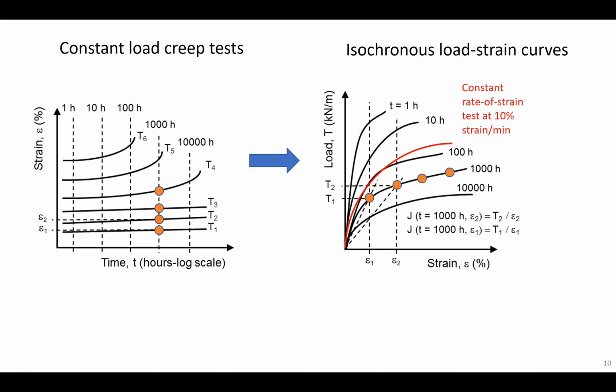Now, superimposed on these isochronous load strain curves is the constant rate of strain test at 10% strain per minute that I mentioned before. And what you can see is that as the isochronous times increase, this constant rate of strain test falls more and more above these isochronous curves. And it's quite clear that these type of tests cannot be used to capture the rate-dependent behavior of these materials.